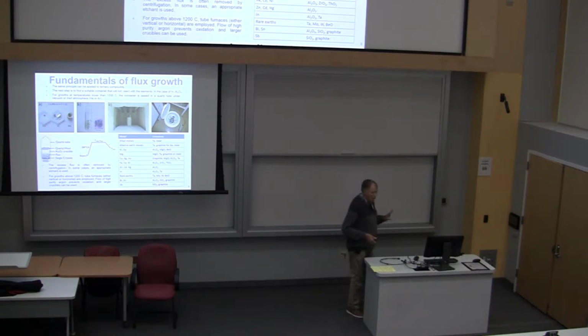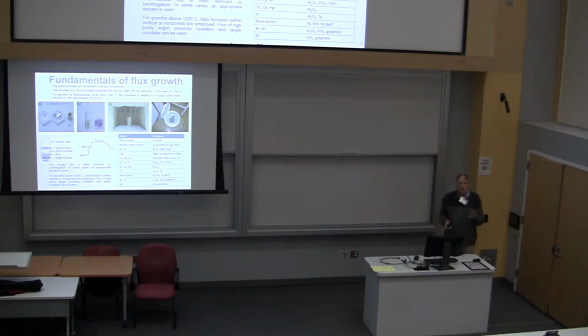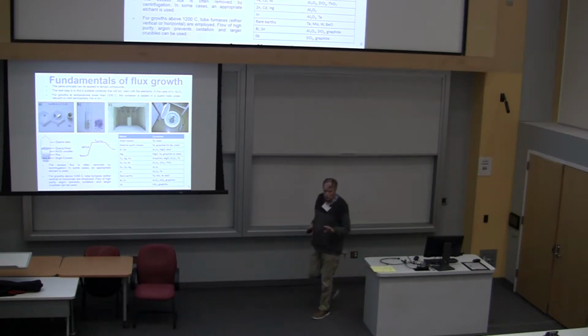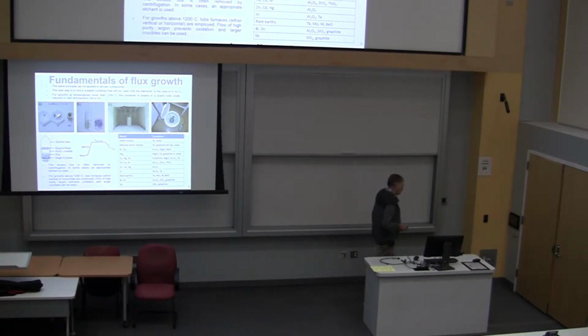In the early days when I was growing up, there was high Tc, which was 17 degrees for superconductivity. All the compounds that had the highest Tcs then were the A15 crystal structure. And the A15 crystal structure, in fact, is not an elemental crystal structure, but it was believed to be a crystal structure of elemental tungsten, which turned out to be W3O. But C15 was one of these Laves phases, in this cubic Laves phase. So this particular research field in condensed matter got going in a particular way when I was trying to grow cerium Laves phases out of indium.